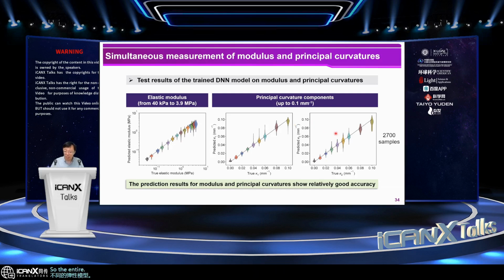So the entire data consists of 30,600 samples. This slide illustrates the results of the testing for 2,700 samples. So you can see very good prediction of the elastic modulus in a very broad range from 40 kilopascal to around 4 megapascal. You can always see quite good prediction of the elastic modulus.